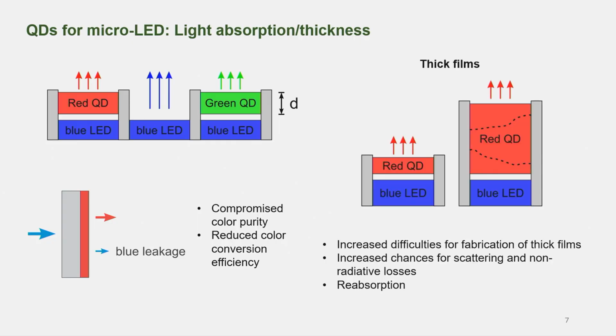Also, you cannot make it infinitely thick to avoid blue leakage, because a thicker film is always going to be hard to fabricate in a very uniform way. Making it thicker also gives you more chances to create defects and scattering centers and non-radiative losses. And finally, especially if the quantum dot doesn't have 100% yield, you also need to consider the reabsorption and reemission process. So this also brings down your color conversion efficiency.